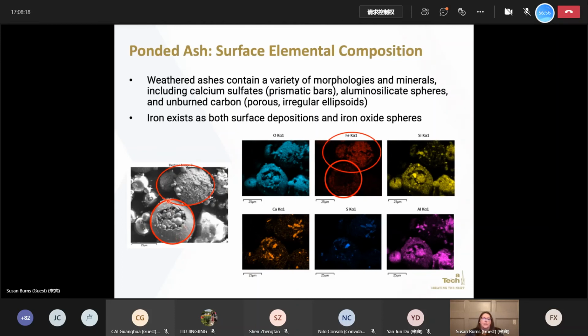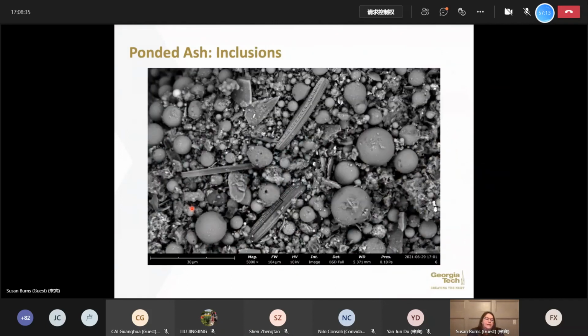In this case, the particle here, where we see the cenospheres inside the larger cenosphere, has a surface coating of iron, while this particle here is actually an iron sphere. So generally in most ashes that you'll deal with, you'll have quite a reasonable percentage of iron oxide present as well. In addition to that, in these ashes, which were disposed of in these open ponds, what you will see is formation of other things. We get microbiological activity, and you can see here that we have inclusions, which are diatoms present in the ashes that we have. These are the relatively near surface ponded ashes that we've dealt with. Very common phenomena. We also see formation of other mineral phases, and you can see here that we've got some other very fine ground particles as well.